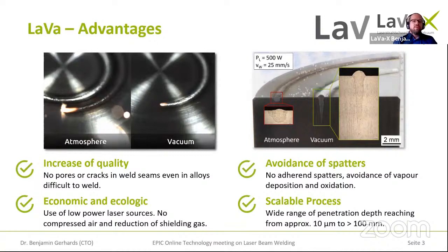So you can see with the same amount of laser power, we can achieve a much higher penetration depth. This is due to the fact that in vacuum, the evaporation temperature of materials is significantly reduced. We are talking about roughly 1000 degrees Celsius for iron and aluminum. So we have the possibility to increase the penetration depth, but on the other hand, we can also reduce the laser power that we need to reach the same result for the weld. And this gives us a couple of benefits for our process.